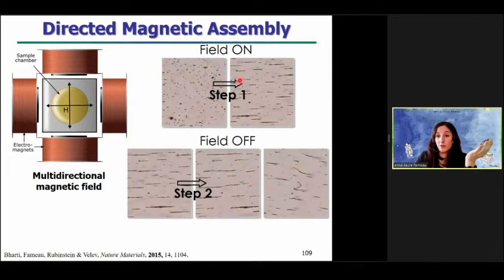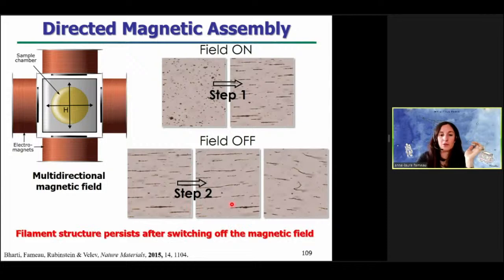Then we just turn off the magnetic field. So we remove the field-induced attraction and we relax the extended chain. And what you observe when we turn off the magnetic field is that the filament structure persists after switching off the magnetic field. So there is something that binds permanently the nanoparticles together. And you can clearly see that the filaments are very flexible because they are undulating inside the surrounding medium after switching off the magnetic field.